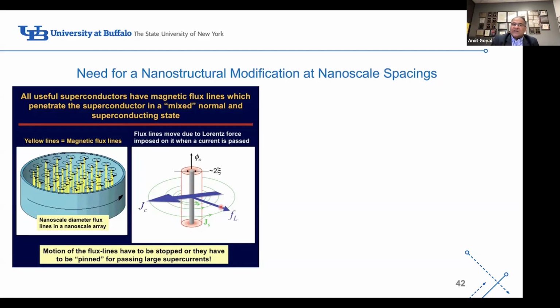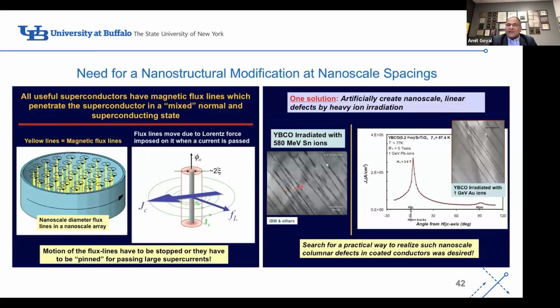So the name of the game was, how can we make these magnetic flux lines going through the superconductor immobile? And again, another thought experiment done at IBM. They took a single crystal of a superconductor and bombarded it with heavy ions. And when they did that, they created these amorphous damaged tracks. The ions went through the superconductor, damaged it, and created amorphous tracks, which were nanoscale in diameter and at nanoscale spacing. This is 50 nanometers here.